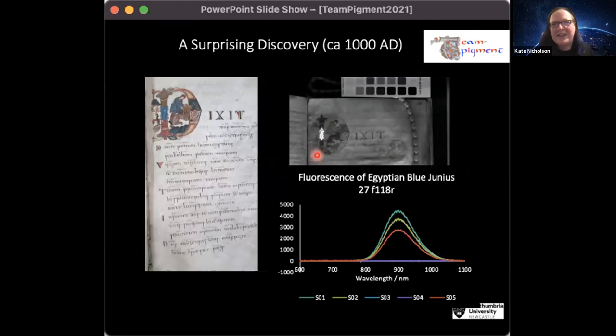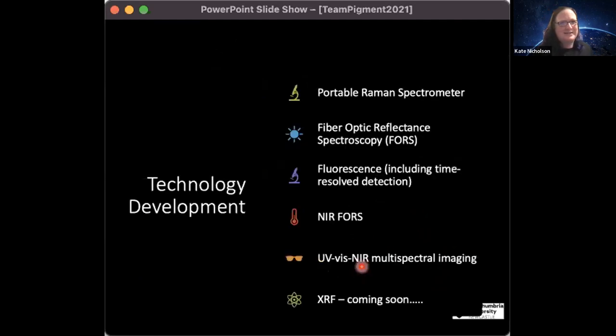So I reconfigured the spectrometer a little bit and measured the fluorescence spectrum of it. And the purple flatline is from the chap's robes, just as a double check that there's no Egyptian blue hiding in there. So we see this fluorescence, this emission of light in the near infrared when it's illuminated by normal light. Very unusual.